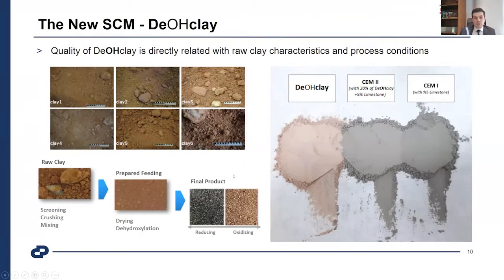There's a range according to composition and mineral formations, between 650, 700 degrees up to 900 degrees. It's related to what I explained. It's tailor-made: the process design and the recipe are related to the raw material.